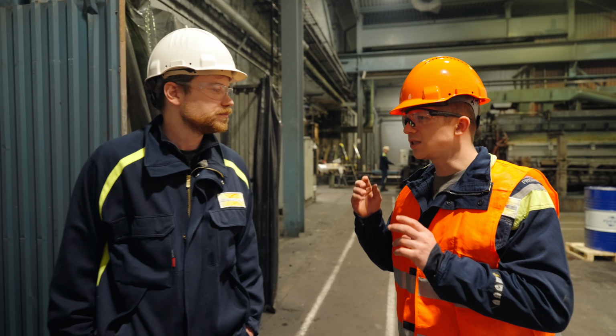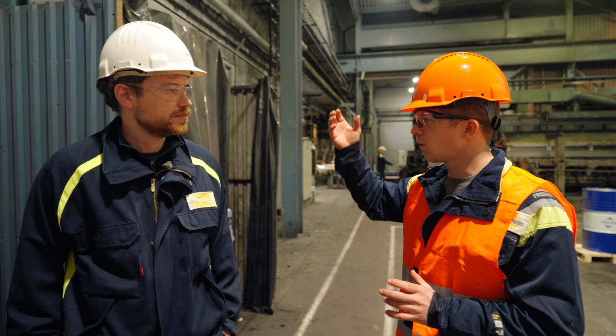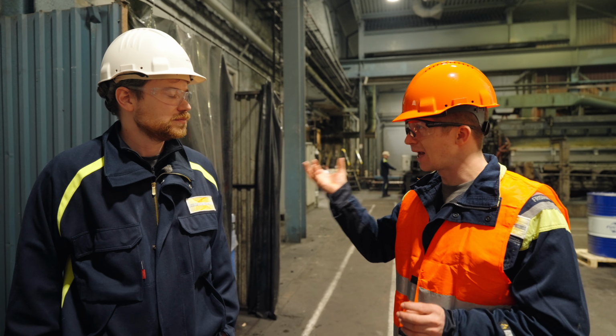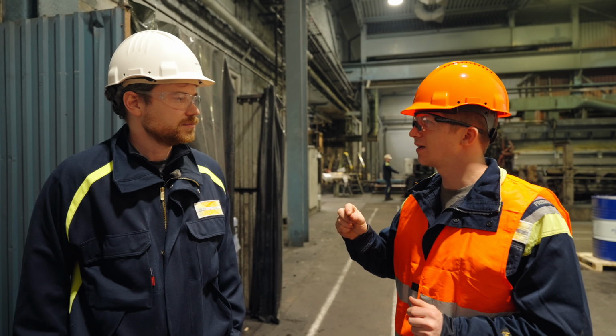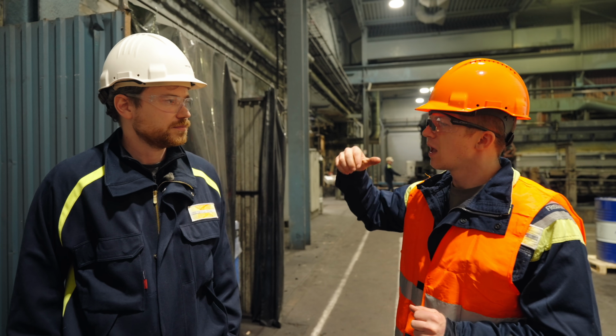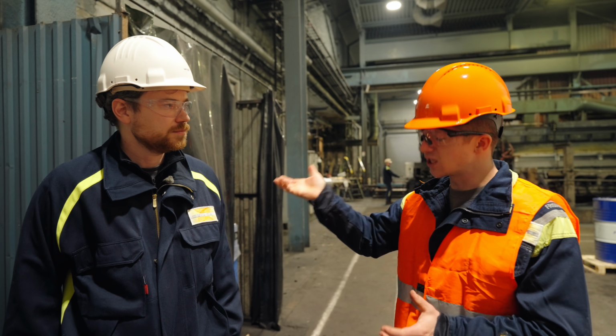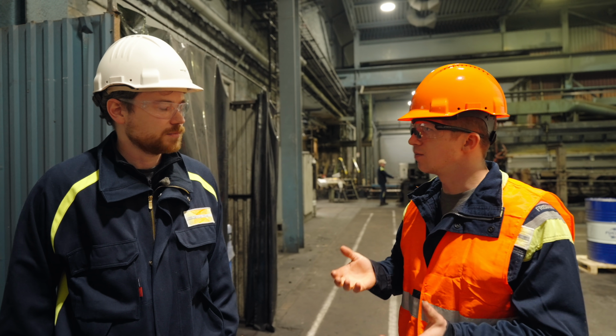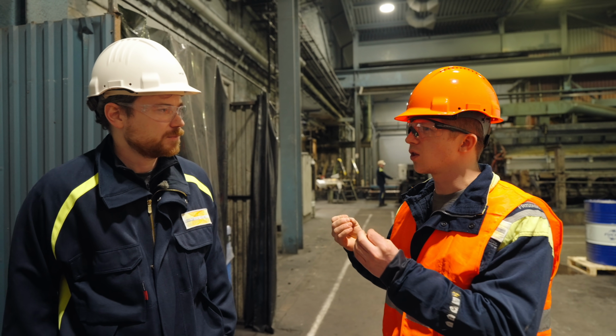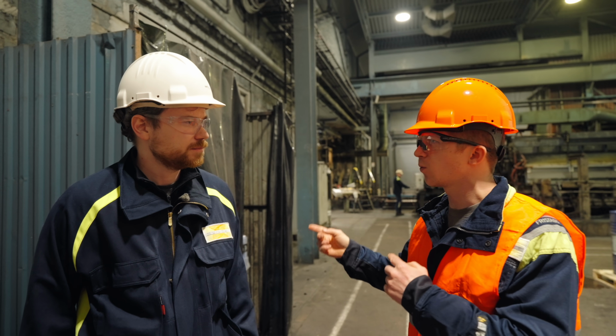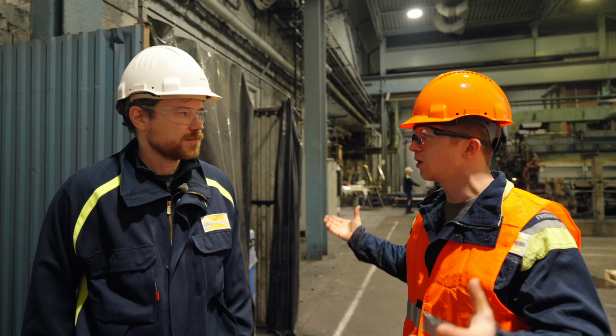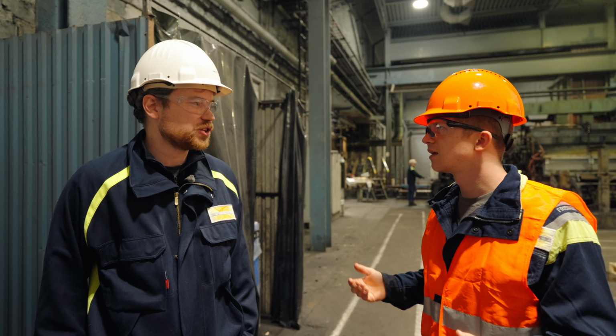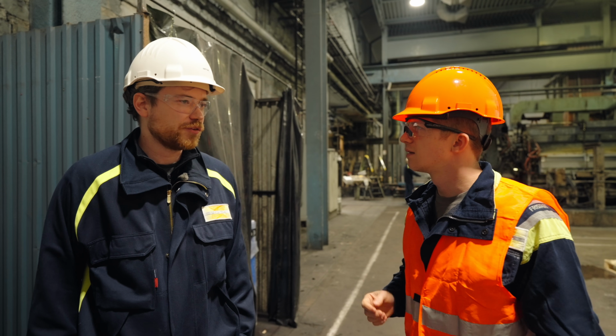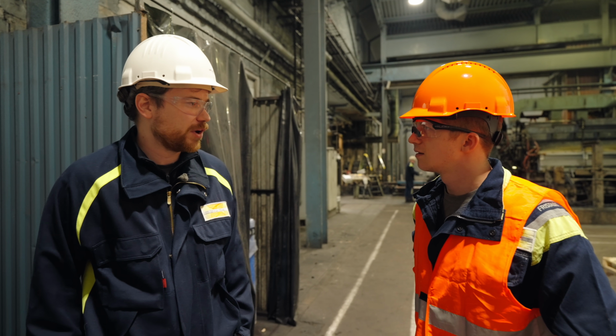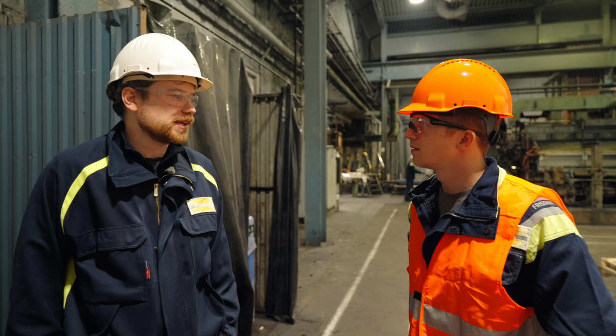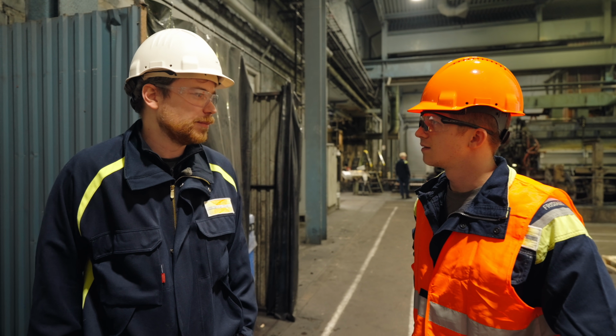So what is different in how your molten steel alloy turns into a powder as compared to when your molten steel alloy is poured into an ingot mold? What's different about how that works that means that you get a better result from the powder than you do from just letting it cool in a big bar? Yeah, it's all about the solidification time in this instance. So if you're making an ingot that is several hundred kilograms large, it takes 30 plus minutes for it to solidify inside the ingot mold.